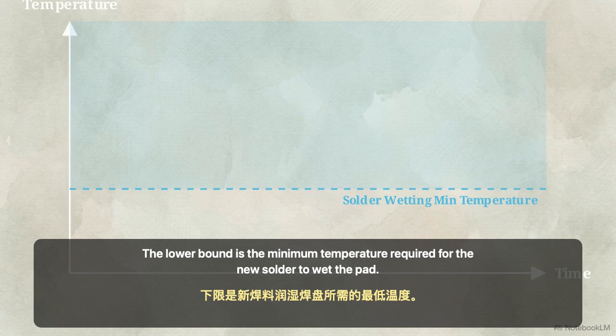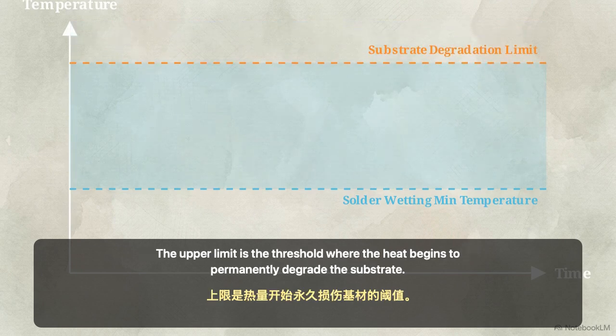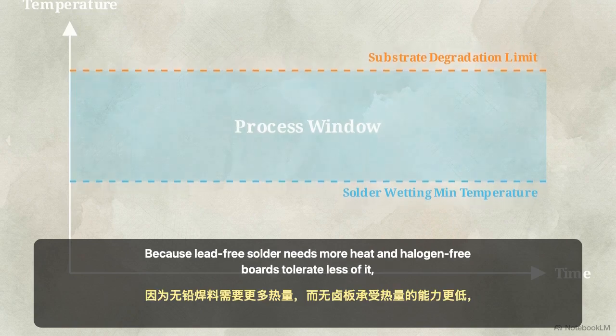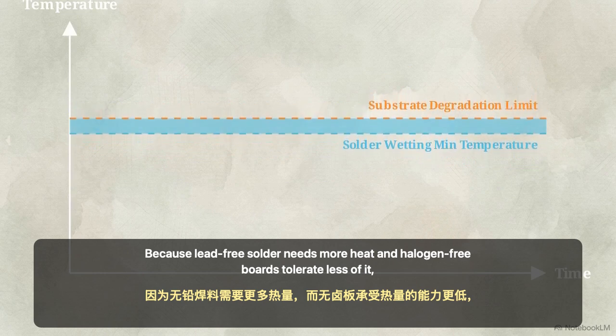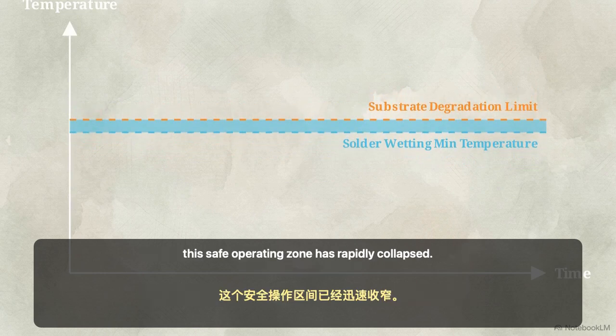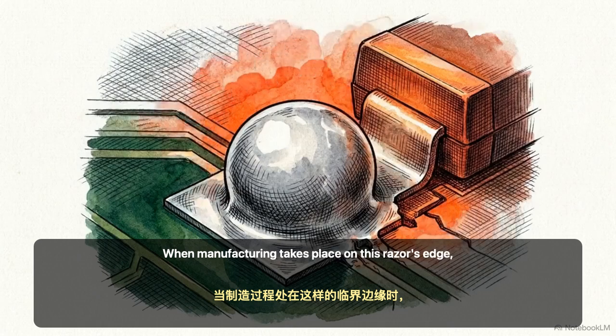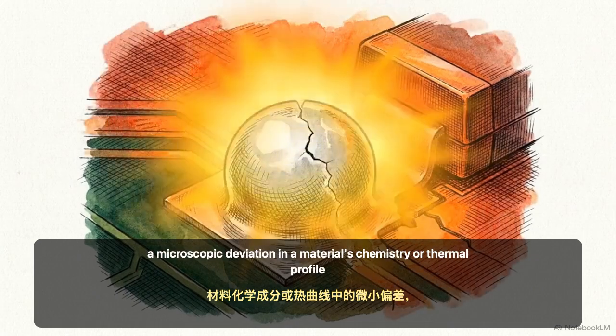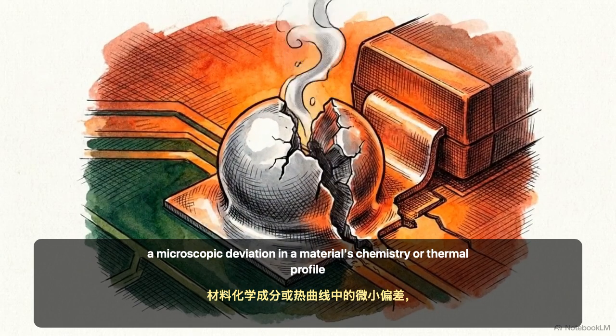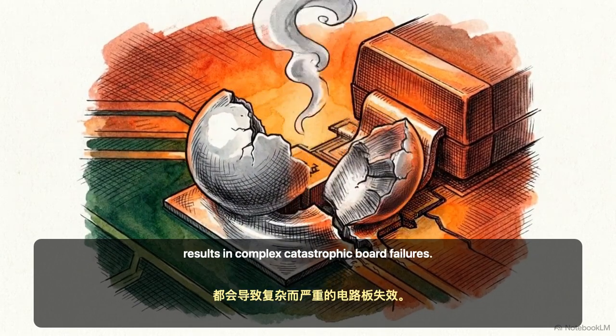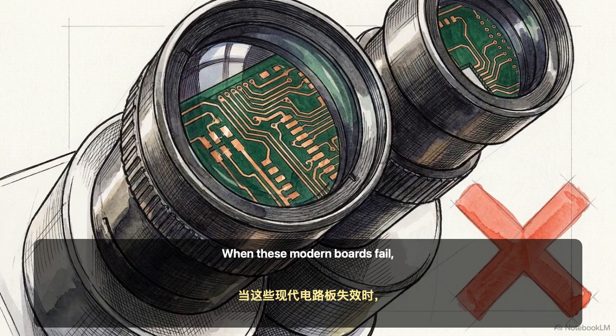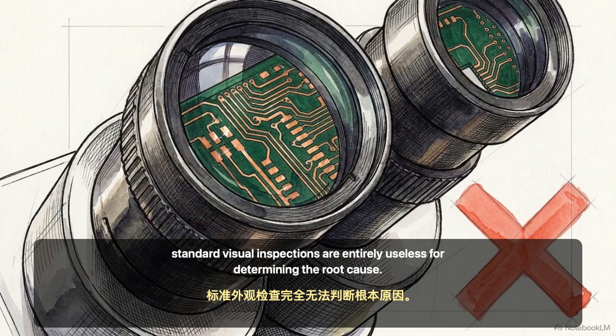The lower bound is the minimum temperature required for the new solder to wet the pad. The upper limit is the threshold where the heat begins to permanently degrade the substrate. Because lead-free solder needs more heat, and halogen-free boards tolerate less of it, this safe operating zone has rapidly collapsed. When manufacturing takes place on this razor's edge, a microscopic deviation in a material's chemistry or thermal profile results in complex, catastrophic board failures. When these modern boards fail, standard visual inspections are entirely useless for determining the root cause.